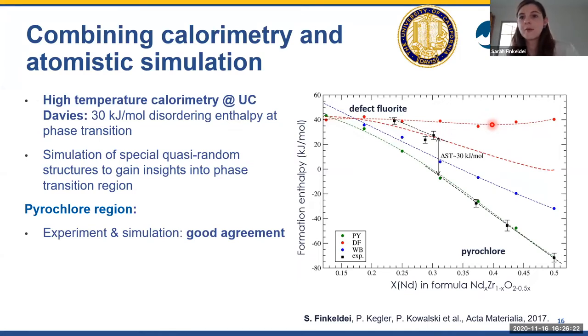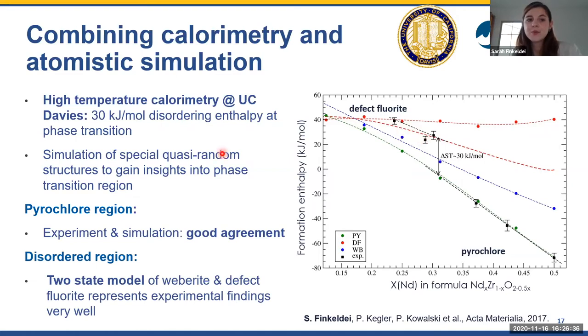And with the knowledge that we obtained, we thought maybe a Weberite would do the job, but you can see that the fit with the Weberite structure also led to really not a good agreement with our experimental data. So what we ended up doing is setting up a two-state model of a Weberite and defect fluorite structure.